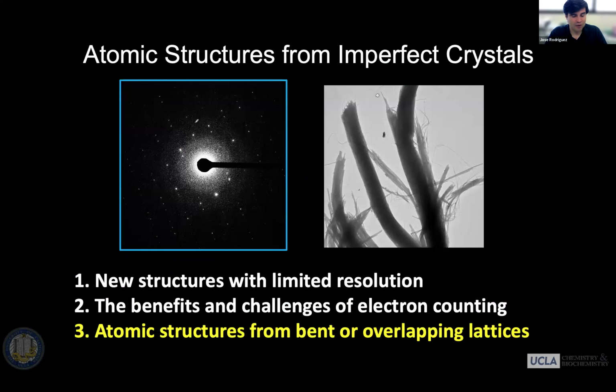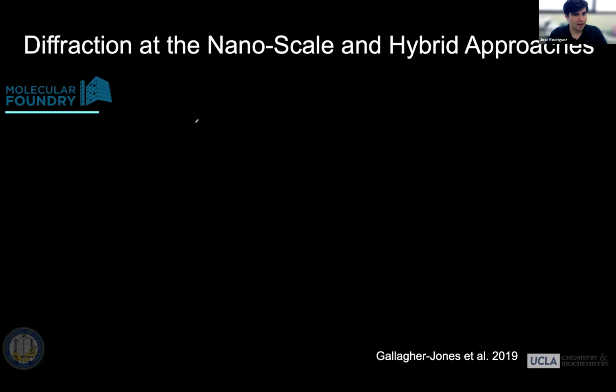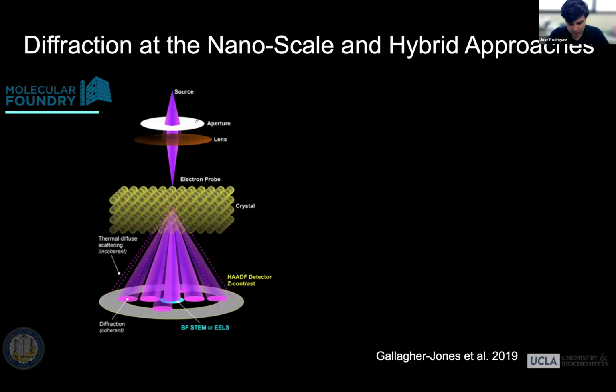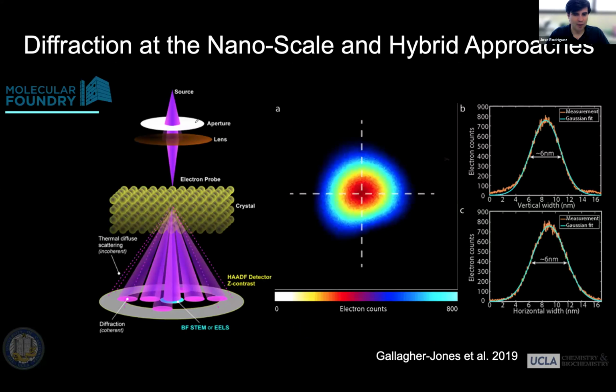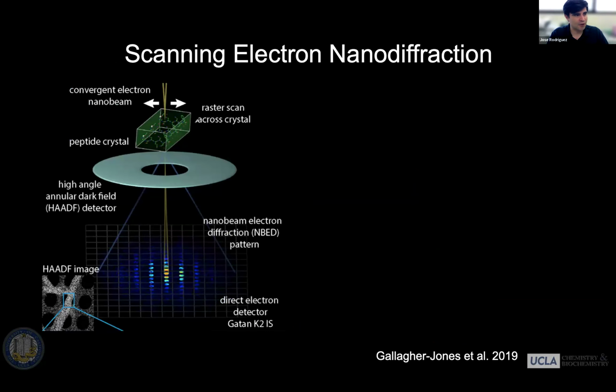In this third section, I'll talk more about the use of some degree of automation and the ability to scale down the experiment even further to map subregions of crystals that may have some pathology in them. And so a lot of this has been work that's in collaboration with Molecular Foundry. And there we're able to use the microscopes, in particular the TEAM microscopes, to shrink the electron beam and basically make a parallel beam that is very narrow and has a very small footprint on the order of about 5 nanometers, full width half max, and illuminate subregions of a given crystal and then raster scan that beam.